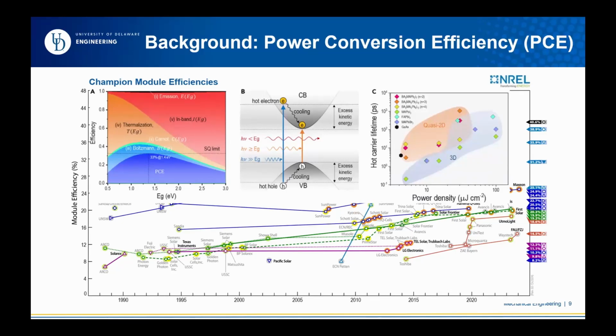This Shockley-Queisser limit. They did some calculation in 1961, published the results, and based on their calculation, the single junction efficiency cannot go beyond 33%. Okay, and this limitation is very much accepted by the community. So even after 60 years, it's still popular and practicable just because no one can really go beyond that. Okay, so you can see here 33% at 1.34 electron volts. That is the limitation for this.